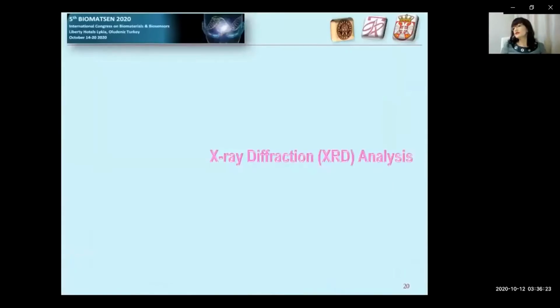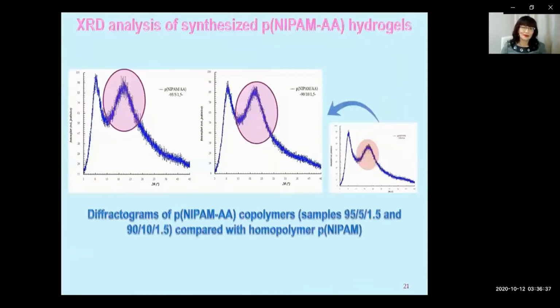X-ray diffraction analysis. Diffractograms of obtained copolymers with 5 and 10 molar % of acrylic acid or methacrylic acid, compared with homopolymer poly(N-isopropylacrylamide), are presented in the next 2 slides. Firstly, poly(N-isopropylacrylamide) co-acrylic acid. Diffractograms of all samples show similarity, no clearly defined reflections, and indicate semi-crystalline structure.